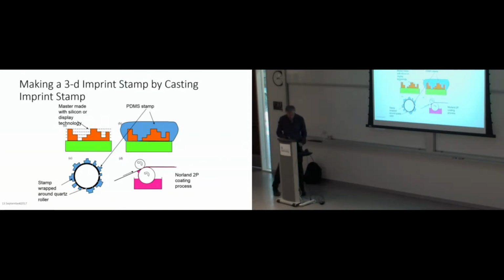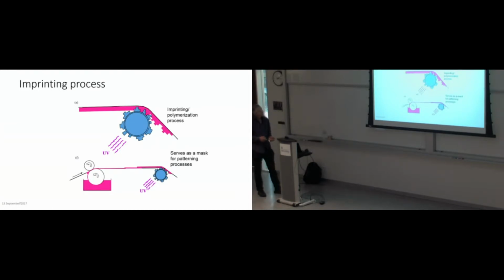And then it's wrapped around this, and so this is an expansion. This is the tightly controlled fluid level. And right when the imprint is squeezing the fluid around, a UV polymerizes it, and so you end up with this polymerized, and then it releases at this point. Because the PDMS and the 2P are somewhat compliant, you can actually get what are called reentrant structures. We could literally make like mushroom tops. In other words, without ripping the top off. If you go slowly enough, you can actually make things that have overhangs if you want. So it releases, and you have this structure.